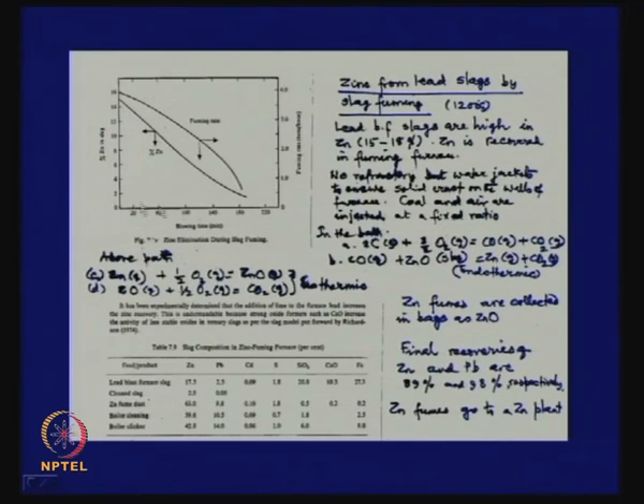Now, here is a small sketch to show how with blowing time the process will proceed. This is blowing time, blowing of carbon and oxygen in slag, and this is percentage zinc in slag. Obviously, the percentage zinc in slag, which is shown here and here, will drop with time, because gradually zinc is going out of the slag phase.